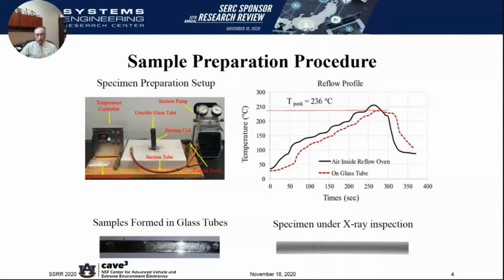The temperature is monitored by a temperature controller. We have a glass tube that's attached to the end of a rubber tubing that's connected to a vacuum pump, and then the solder is actually sucked into the glass tubing to form the specimen. So once the specimen has solidified, then we'll send it through reflow.